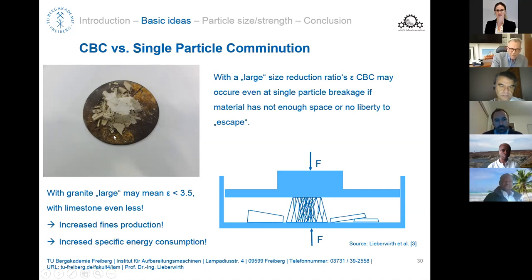And you can see there was enough space on the outside, so the material could have escaped, but it did not, because of friction and the structure of the material. Essentially, the structure of the material looked like this, and inside the material a particle bed had already formed. You could see it in the particle size distribution, because you produced a lot of fines in the material, which is important to understand for many of the comminution processes, particularly for coarse crushing.